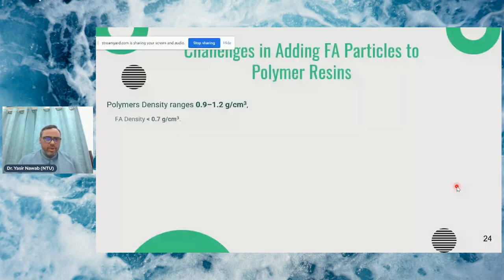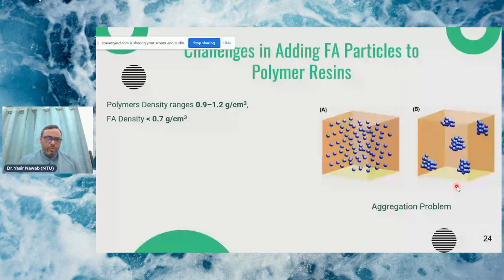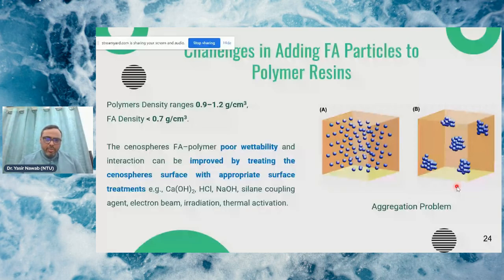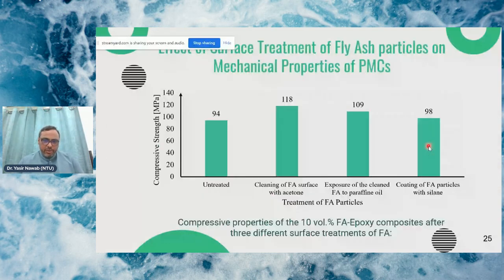Another problem, in fact, is that the density of polymer ranges between 0.9 to 1.2 gram per centimeter cube. The density of fly ash, in fact, is lesser. They are very light particles. When we try to mix them, there is a problem of wettability, and in general for composites, aggregation of particles as well. So in order to improve that, in composites we do surface treatments of particles. There are some surface treatments of particles which are being reported.